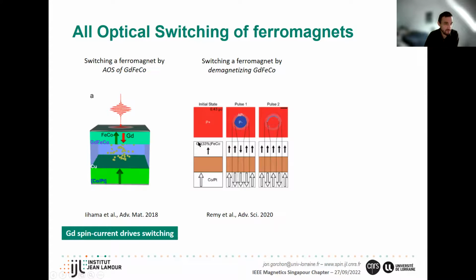So you have the gadolinium iron cobalt layer on top, the cobalt platinum below. And when you shoot one time in the center, you get these 2 rings, P and AP minus. And so if you notice in the surrounding part here, the gadolinium iron cobalt remains up magnetized, but the cobalt platinum has switched. So you don't even need to fully switch the gadolinium iron cobalt. Just the spin current induced by the demagnetization of the gadolinium iron cobalt is enough to switch this bottom layer. So no all optical switching is necessary.